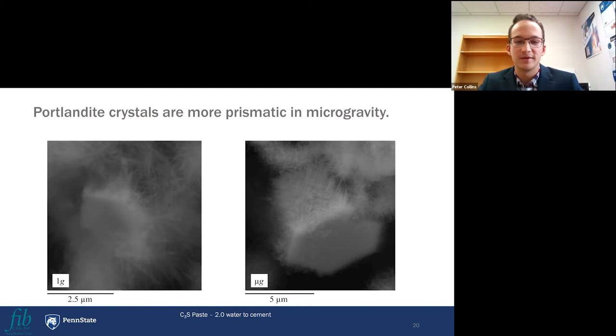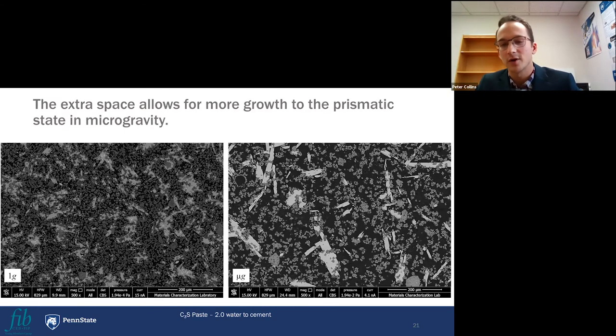And so this can be visualized very well when you look at a polished cross section of these samples. Here it's very apparent that there was a reduction in bleeding in microgravity and an increase in the overall porosity. I believe the terrestrial gravity sample had a porosity of around 45%, whereas this microgravity sample is almost 70% porosity. And you can see the difference in the morphology of the calcium hydroxide, the portlandite crystals, the CH crystals.